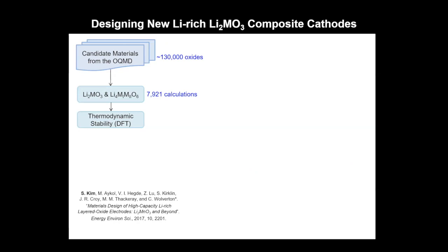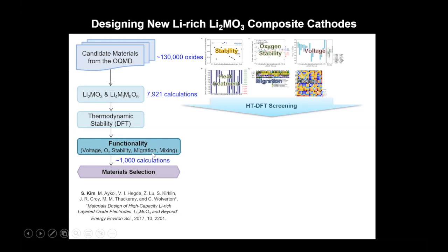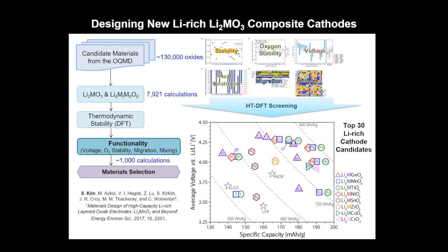So when we put all these things together, it looks like the screening strategy that I talked about. You start with a large number of candidate oxides in the OQMD. You narrow that down to the compositions that you're interested in. I didn't talk about this, but in addition to the single metal compounds, we looked at double metal compounds as well, and the mixtures of those materials. And then we start applying our screens. We screen for thermodynamic stability. We screen for properties of the function, like the voltage and so forth, and the oxygen stability, the metal migration, and so forth, and ultimately wind up with a small number of candidates that look promising for these applications, and can plot this, for example, in this plot of voltage versus capacity to illustrate some of the materials that emerge through this screening strategy. Okay.